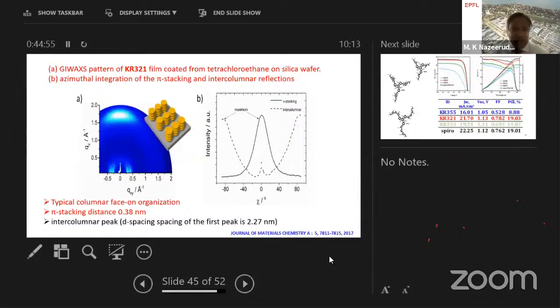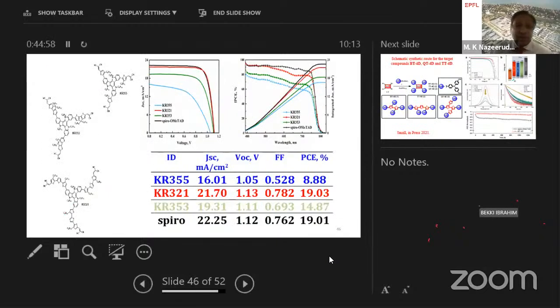Next slide, please. Yes, here, just focus on KR321, which has 19% efficiency. KR321 has three thiophene groups on the triazatruxene, and similarly, spiro-OMeTAD under the same conditions gives a similar efficiency. But the difference between these two hole transporting materials is that spiro-OMeTAD is doped and KR321 is an undoped molecule. So this is the beauty of these undoped hole transporting materials, to see enhanced power conversion efficiency and stability.